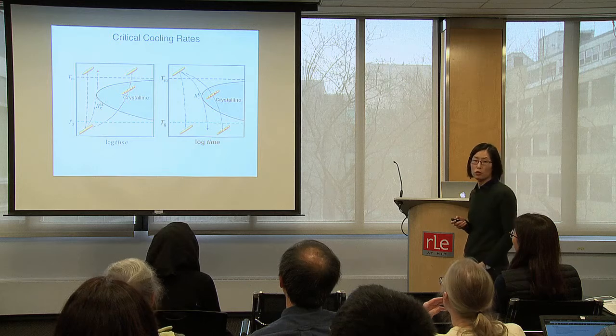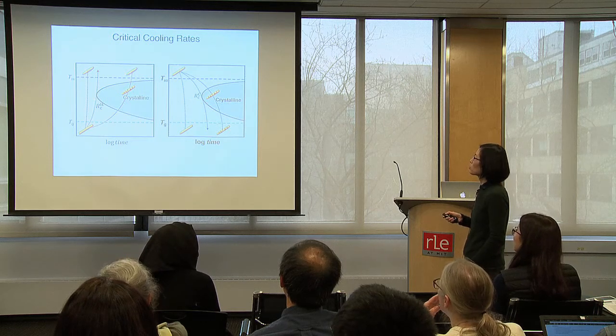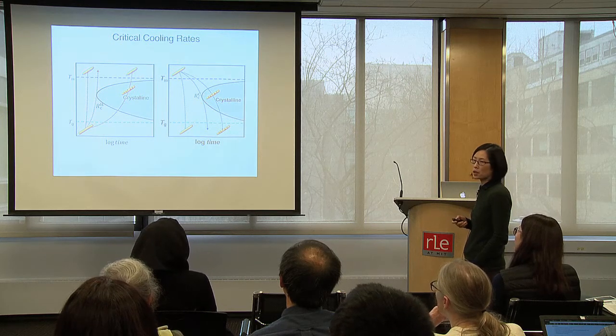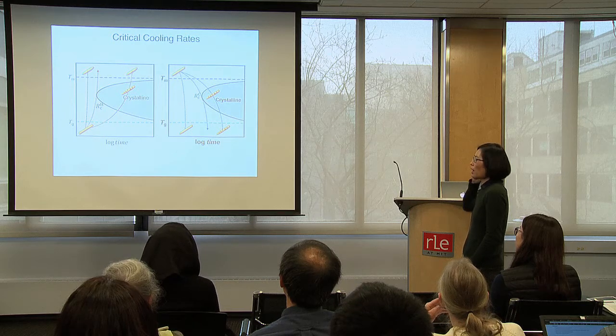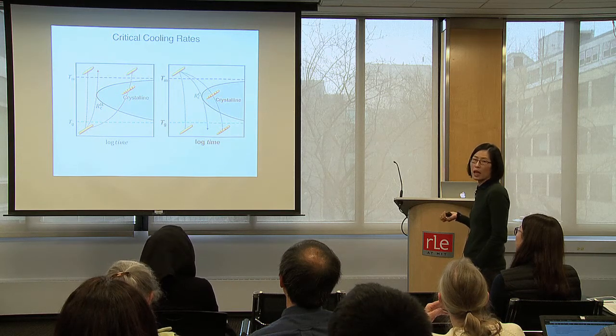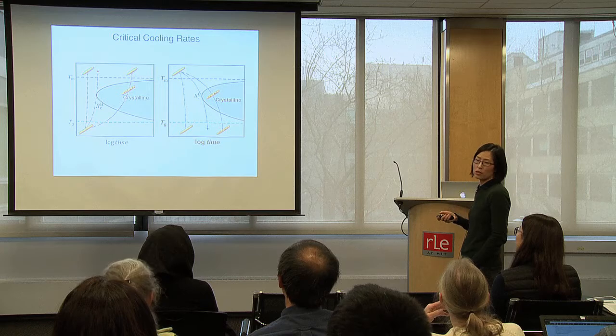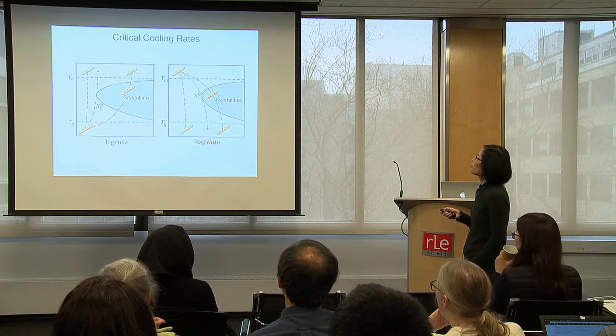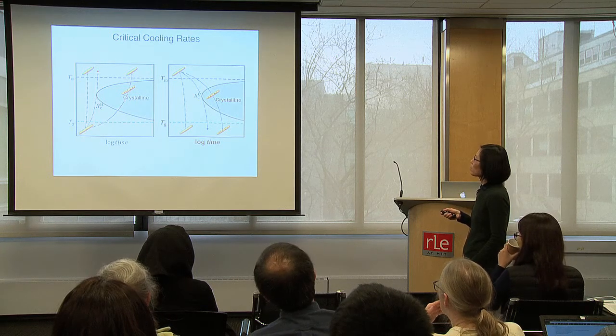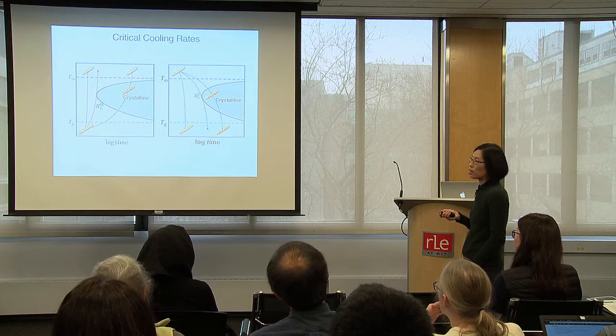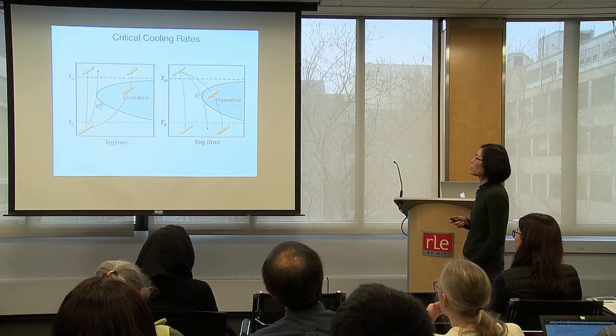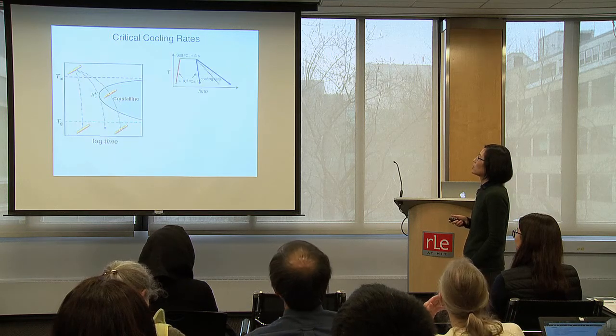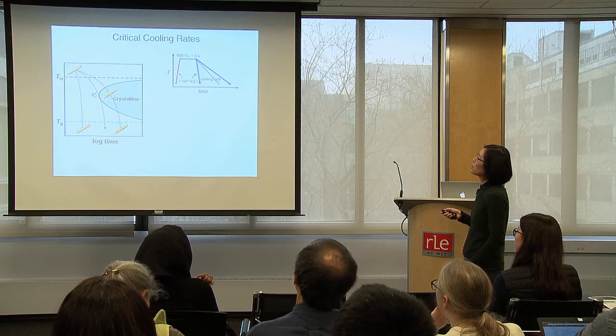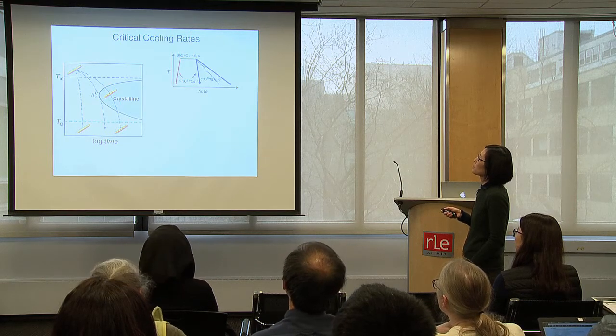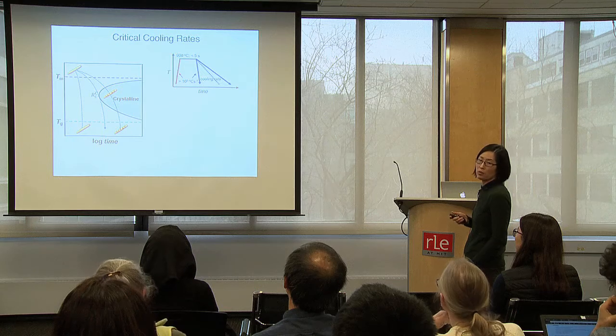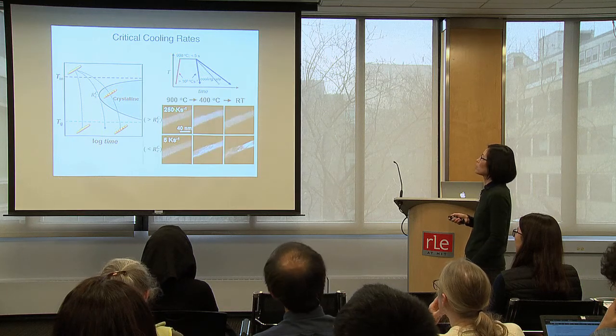You can do the same thing for the cooling. If you quench the liquid, then it becomes glass. So for silicon oxide, silicate glasses, the quenching rate can be rather slow, right? If you quench it slowly, it's going to become crystalline. And then again, you have a critical range. Okay? So we repeat this, but now here we go to 900 degrees Celsius, and now we vary the cooling rate.